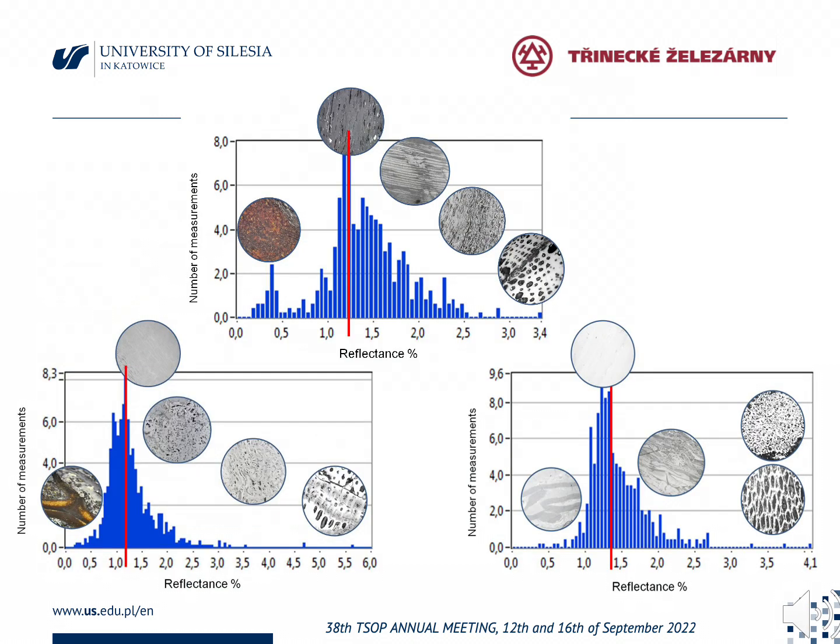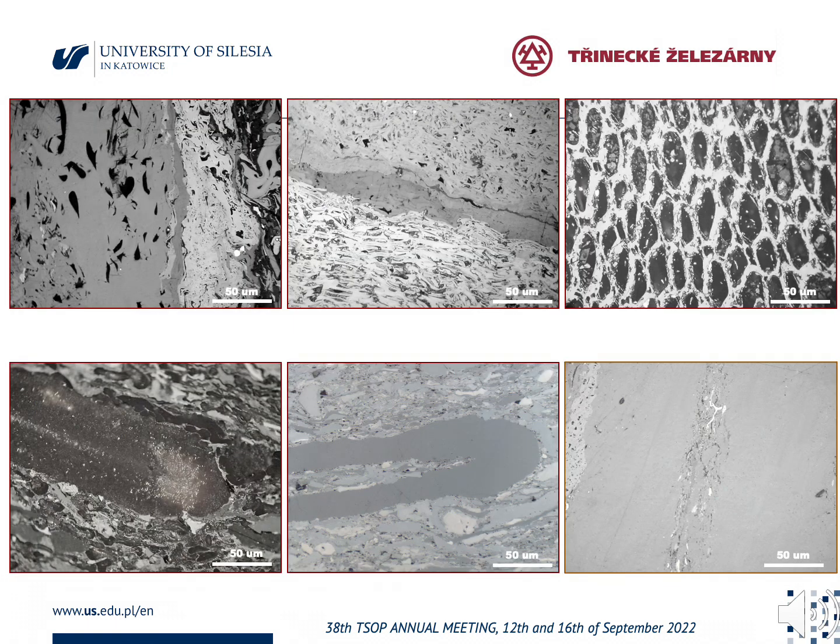In this respect, the application of all-maceral mean reflectance as a threshold for determining the reactive portion of maceral in the sample, and simultaneously measuring vitrinite reflectance, has proved to be a useful tool for both type and rank determination. Contrary to maceral analysis, which is based on subjective operator evaluation, the scan analysis provides an objective identification independent of the human eye. This subjectivity influences the identification of the reactive portion of the inertinite group of macerals and the accuracy of the reactive-inert ratio evaluation.